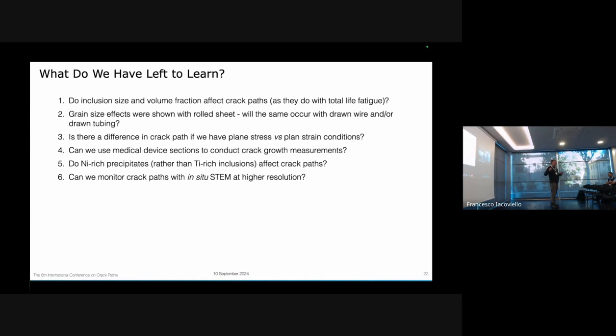And if you remember the Takahashi diagram, that's over in the area where we have to be concerned about those defect sizes. When you're in about the less than 10 micron range, now we're actually getting, from a total life perspective, increases of 200% in our fatigue life. Okay? So there have been improvements, but you know what?